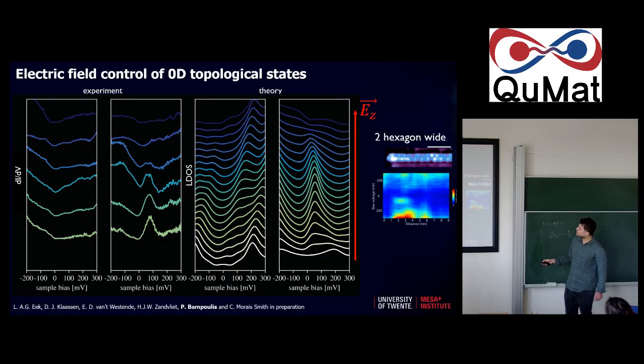And you see the following happening. You see that the end state disappears. It's gapped out eventually. So you go from having the state to not having the state, and the gap is closing and then reopening. And you see the same thing in the experiment. Here you have your end state, and then it's gapped out at the high field situation. So using this electric field, you can think of having a switch, a topological switch, going from a zero-D topological state to a system that does not have this state, so to a trivial system.